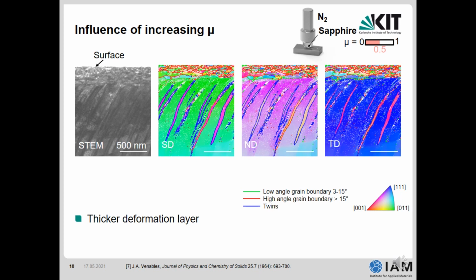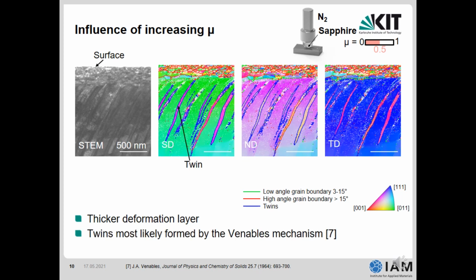We see here also different microstructural characteristics. First of all, we have here really large twins, and the size of these twins is also one point why I think that they were formed by a Venables mechanism, and the other point is that some of these twins are not interacting with the grain boundary or the surface, and the Venables mechanism usually forms in the grain interior.